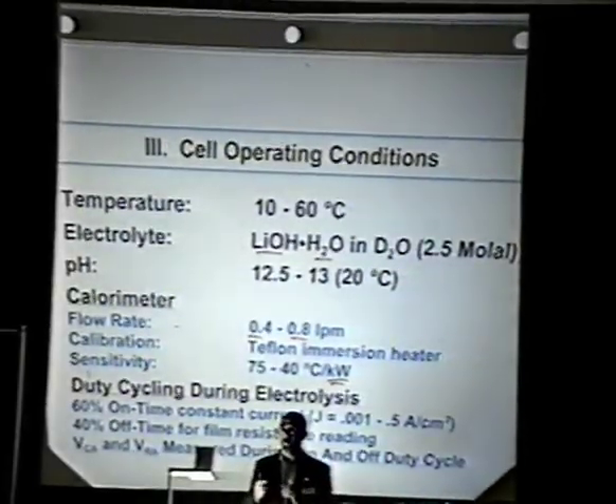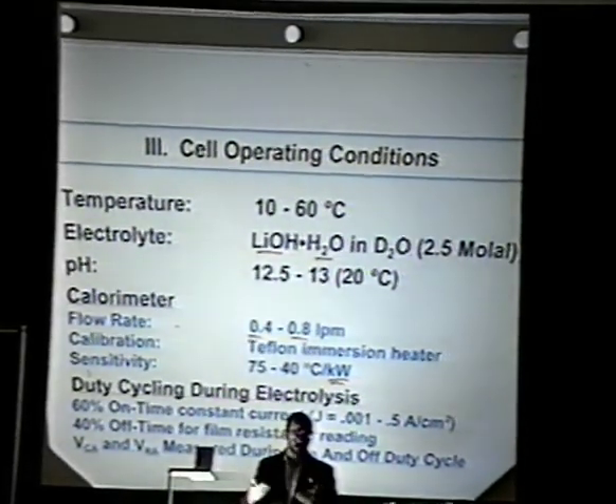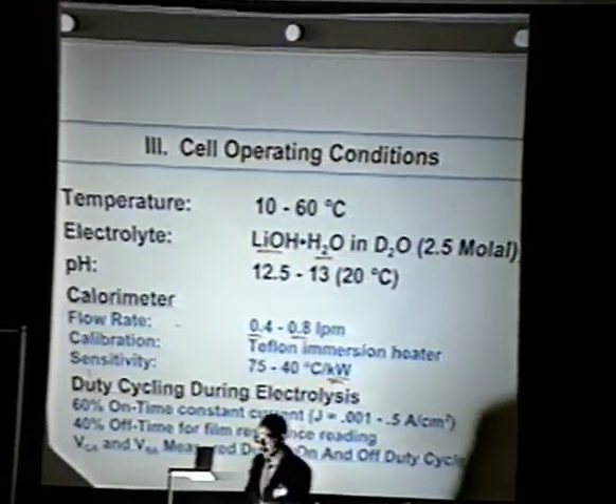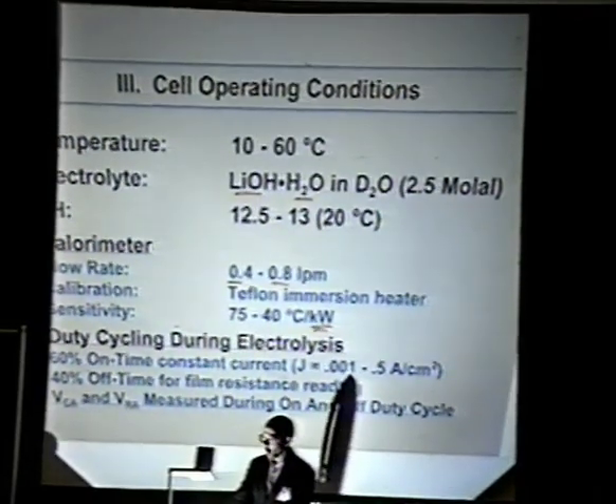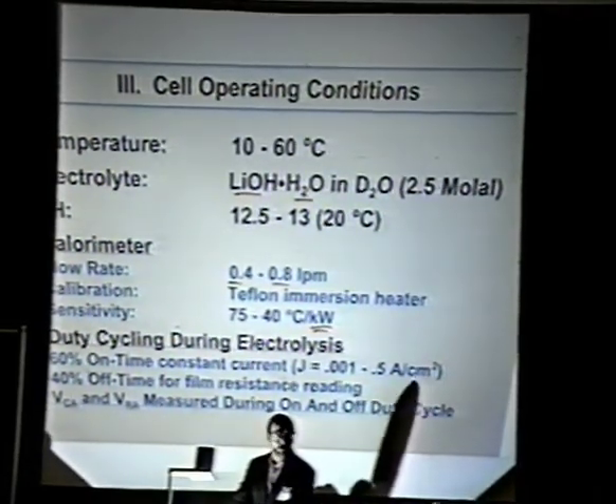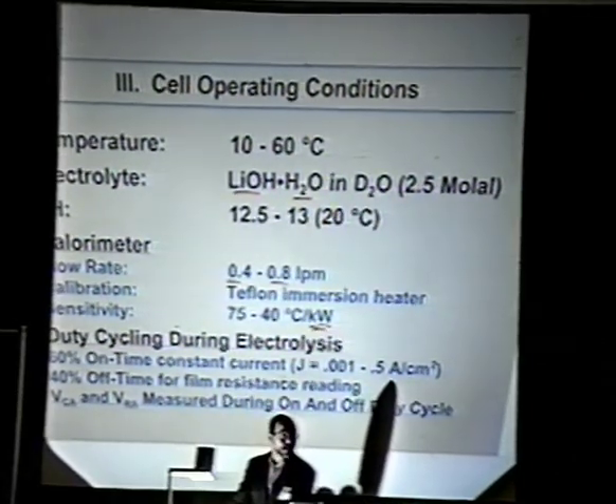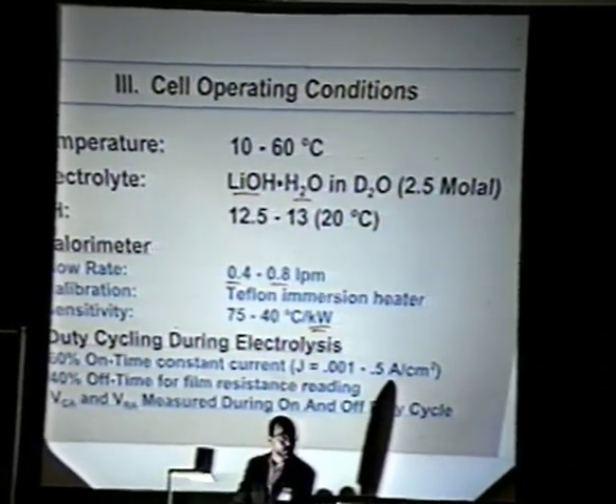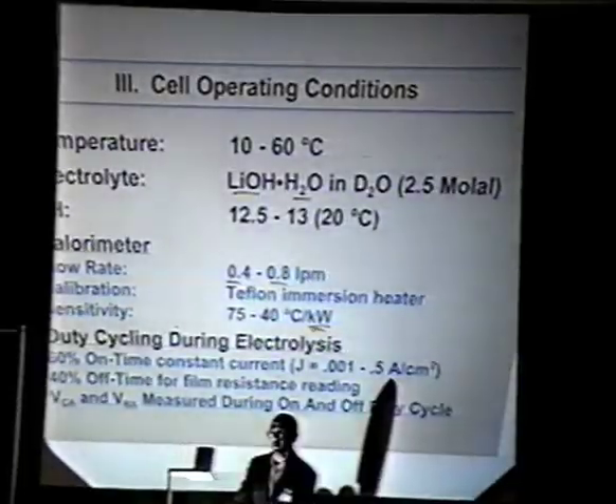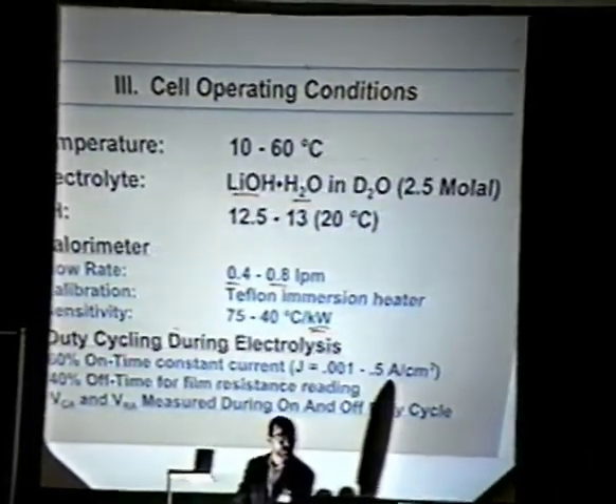There's other runs where you have to electrolyze it quite a bit, and then during some of the non-electrolyzing time is when the power showed up. That's just external results I've found. But typically I can run anywhere from about a milliamp per centimeter squared up to maybe half an amp. That's the most I've ever done. Because a lot of times when it doesn't produce heat, you start trying all kinds of things, just to see what you can do to it.